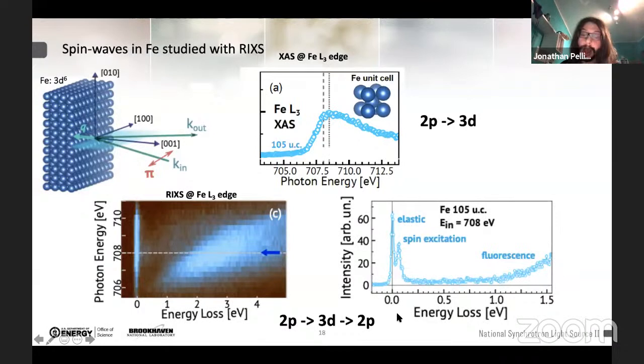Now, having observed this, we decided to investigate how the spin excitation dispersion is present in a thin film of iron, which has bulk characteristics. So in this case, we selected a 105 unit cell iron film, and we measured the dispersion.